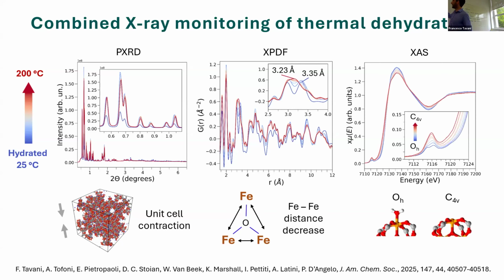And again, of course, the XAS shows very significant differences. These are quite similar to what we had measured in the previous work. As we remove water, going from the blue, the water-saturated MOF, to the red, the water-dehydrated MOF, there is a shift of the edge energy towards lower energies and the increase of a single peak in the pre-edge at the expense of this double peak. This is due to the fact that we are removing the water molecules, so the iron sites aren't octahedral anymore, but are progressively moving towards a square pyramidal configuration.